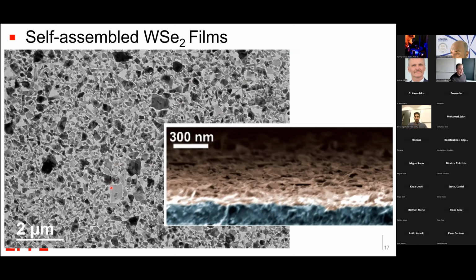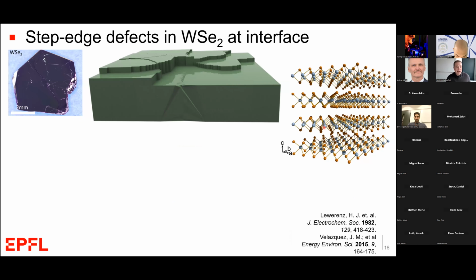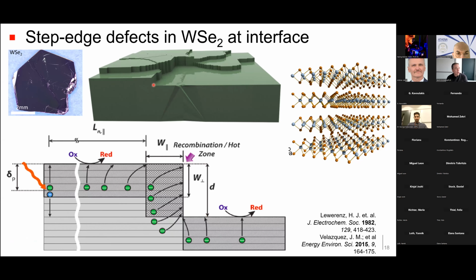And that's due to these edge sites, which have a lot of defects that serve to recombine the photogenerated charge carriers. In fact, this is well known about these tungsten diselenide type films, and it's one of the reasons why the polycrystalline photovoltaic devices didn't work very well in the 1980s. It's also due to one of the problems with these materials, which is that they have a very anisotropic charge carrier transport. Given the crystal structure here of the material, if we look at a typical single crystal surface, it'll even have these step edges. And these step edges represent defects, for example, like the selenium vacancies here, that will cause recombination.